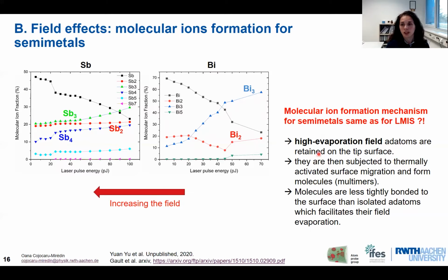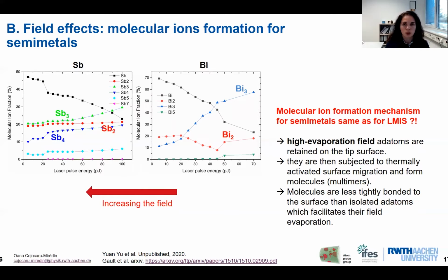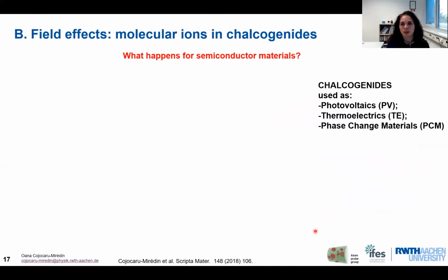Typically, high evaporation field atoms are retained on the surface of the tip. Then they are subjected to thermal activation surface migration and form molecules or multimers. And these molecules, because they are less tightly bonded to the surface, are isolated and easily field evaporated. However, this model cannot really explain what happens for some of the semiconductor materials like chalcogenides.